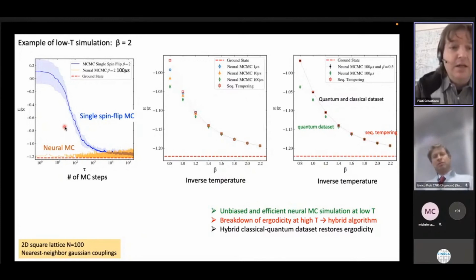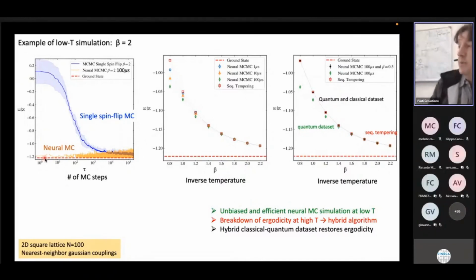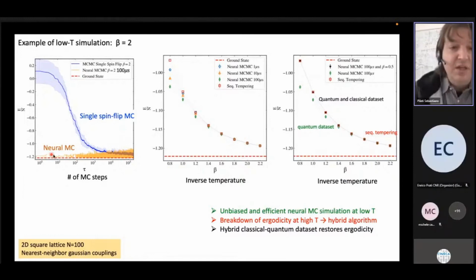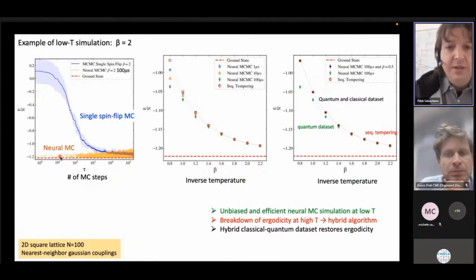So here in the top left, you see an example of a Monte Carlo simulation at a low temperature. So in blue is the trivial single spin flip algorithm. You see that it converges to the equilibrium energy in a huge number of Monte Carlo steps, while the neural Monte Carlo simulation driven by the network trained on D-Wave data converges almost immediately.